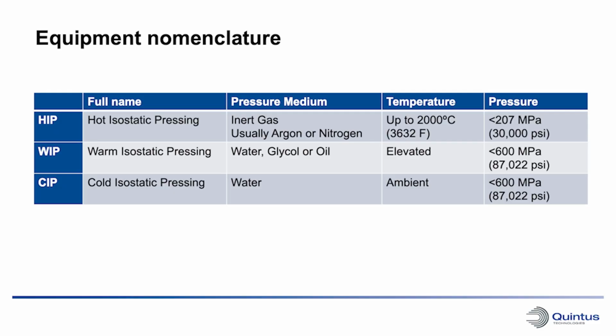Okay, and what kind of temperatures are you going up to, and what kind of pressures? Well, for the HIP units, we go up to maximum 2000 degrees Celsius, and we use argon as a pressure media. And argon is a noble gas, so it will not react with anything in the press, the parts or the furnaces or the machine itself. But of course you can get some impurities into that also, but that will be more like a second question.